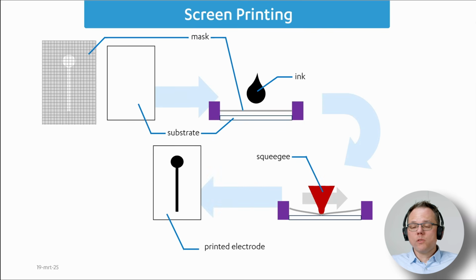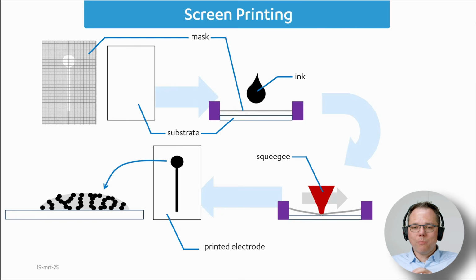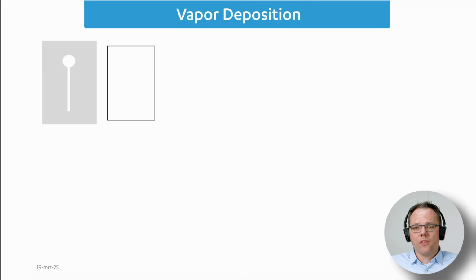Then you cure it, so you warm it up to remove the organic solvent, and you end up with a matrix of polymer binder and conducting particles, like in this blob on your electrode, which forms a conducting, in this case carbon-based, species. These are usually in the thickness range of 25 micrometers, or maybe up to 100 micrometers. So they're rather thick compared to thin film electrodes, which are usually made by vapor deposition.